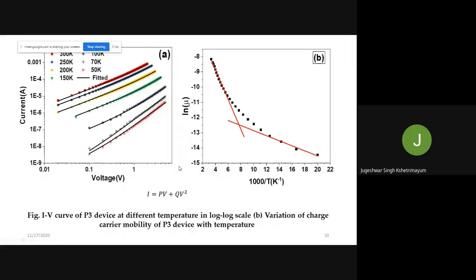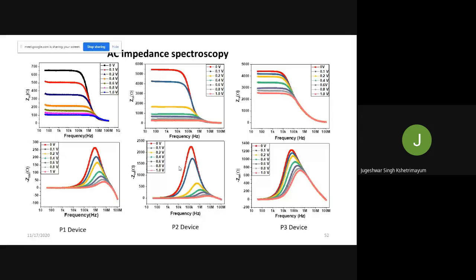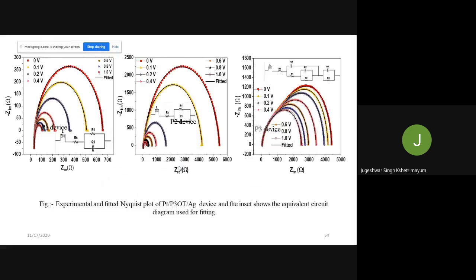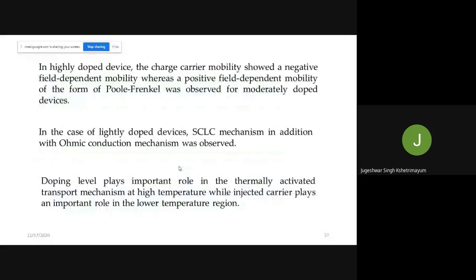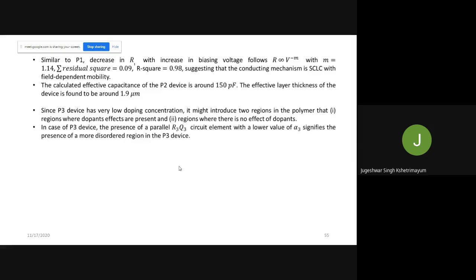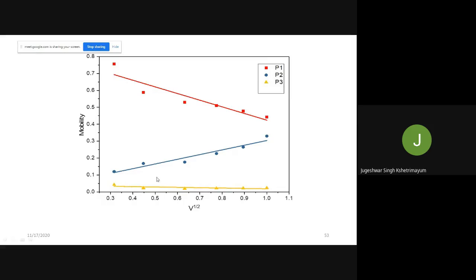But in the earlier two cases, we are not able to see the contribution from the ohmic because the conductivity is high. So this is for my slides, which I don't want to discuss now because the time is not there. In highly doped devices, the charge carrier mobility shows a negative field dependence, whereas the positive field mobility from Poole-Frenkel is observed in the moderately doped devices, which I am showing in this graph. This is negative field dependent, positive field dependent, another negative field dependence, which is what I meant here.